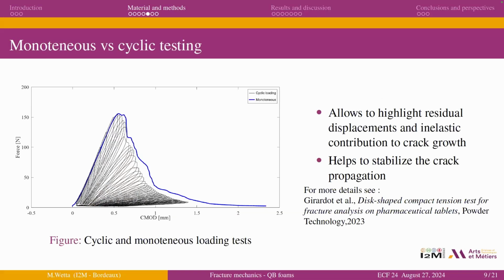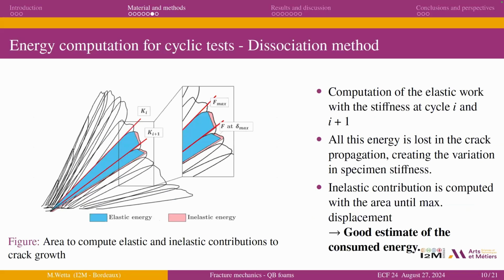For the specific loading, we compare a classical monotonic loading with cyclic testing, because we made previous work on other materials, and we have observed that the cycling helps to stabilize the crack propagation. The second reason is that the cycling helps to dissociate the elastic energetic contribution from the inelastic contribution. So you have a more rigorous analysis of the energetic contribution.